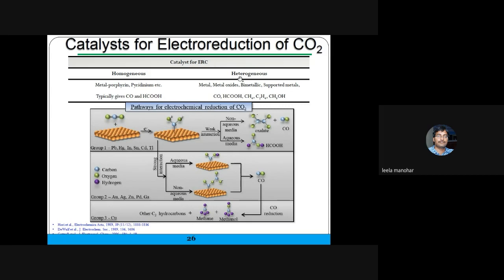The homogeneous, whereas the heterogeneous we have the different kinds of metals and metal oxides. So typically we get CO, formic acid, methane, ethylene, methanol. If you see the pathways, there we have divided the electrodes. Suppose group one: lead, mercury, indium, tin, cadmium, thallium. Group two is gold, silver, zinc, palladium, gallium. Group three is copper.